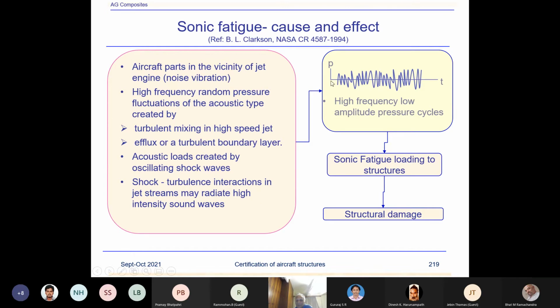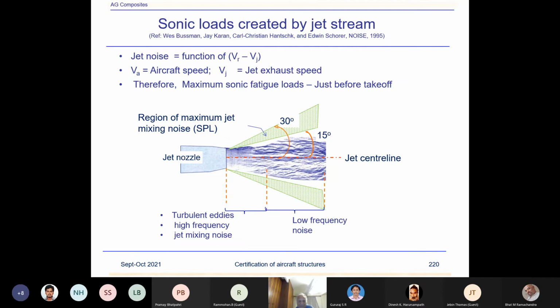So in summary, they create some kind of pressures, because it's a pressure which is causing the noise, fluctuating pressures with time. So high frequency, low amplitude pressure cycles that are converted to the noise we call sonic fatigue loading to a structure, and then structural damage. So essentially, based on this spectrum of loading, the spectrum for the sonic loading is created for every part in different regions, and then they are analyzed for sonic fatigue. What this is showing schematically is a jet nozzle creating exhaust. Usually the maximum noise occurs between 15 and 30 degrees from the center line. So all those parts which are in the vicinity of this are encountering high cycle fatigue.